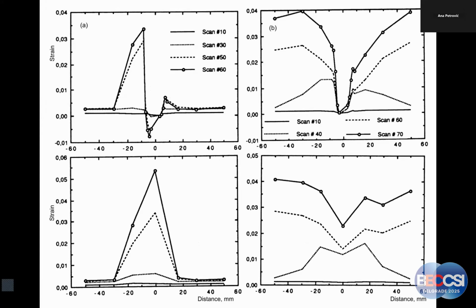Now, a couple of interesting results which show strain distribution on the side of the crack and on the opposite side. And you should notice a difference in these strain distributions, because that difference is actually, as I will show you soon in a simpler example, a measure of J integral. Simplified, even more simplified measure of J integral. So let me explain what I mean.